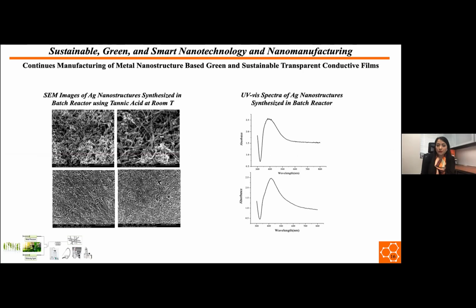And here I'm going to show some of the results from this project. For example, Sina, who is working on this project, has been trying lots of green reducing agents at different reaction conditions. Here is one of the results that he got, in which we were able to produce silver nanostructures, including one-dimensional silver nanostructures that we are really interested in, using tannic acid at room temperature and using water as solvent. Depending on the source of tannic acid that we use, we can get either very long silver nanowires with very high aspect ratio, or nanorods. And the UV-Vis proves that the nanostructures that we are getting are a combination of one-dimensional silver nanostructures as well as silver nanoparticles.